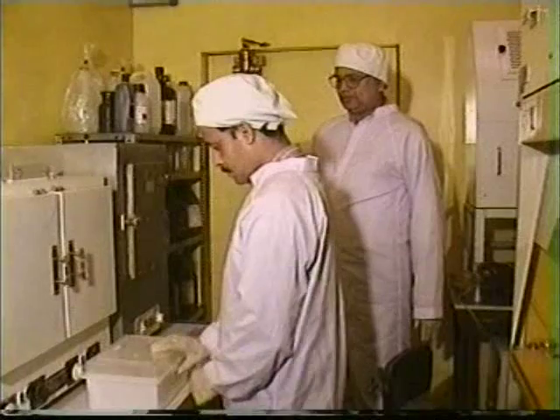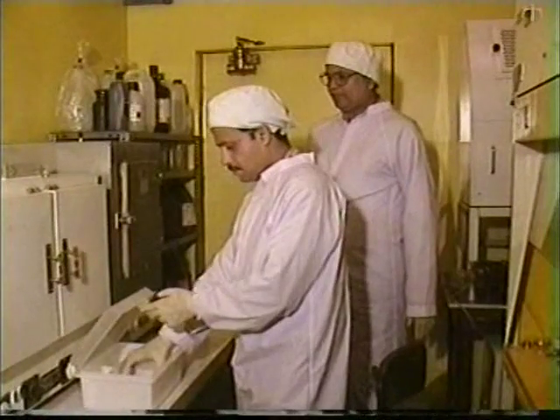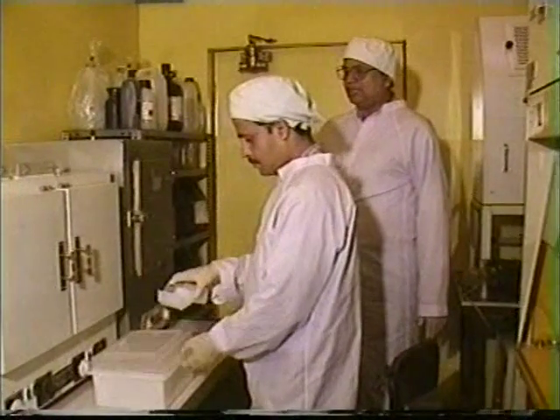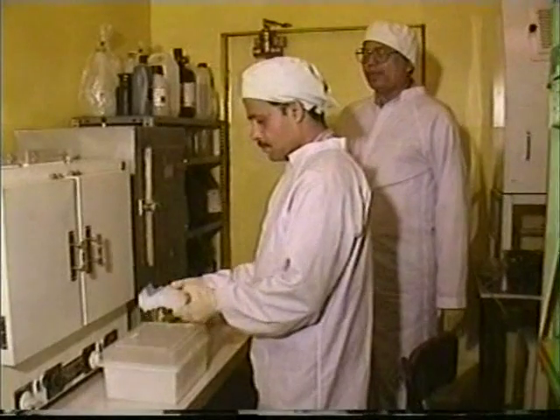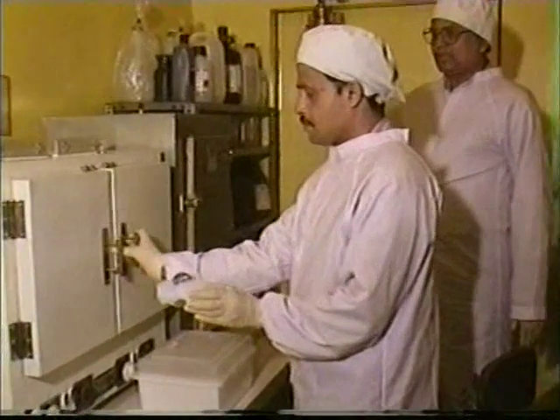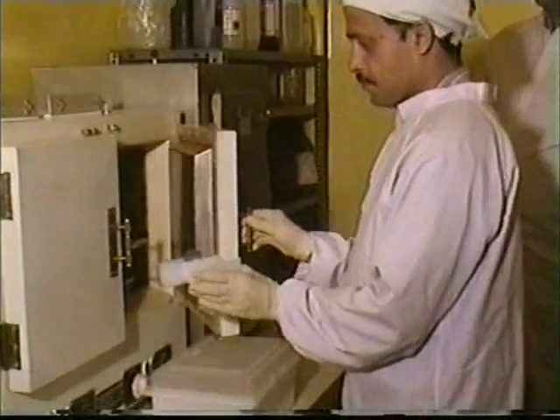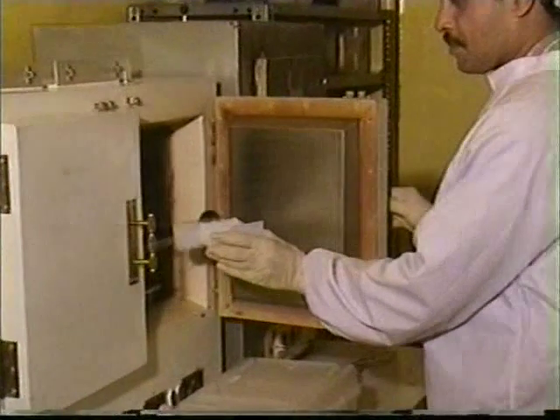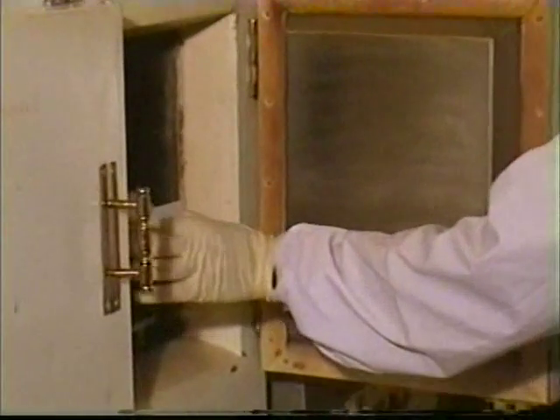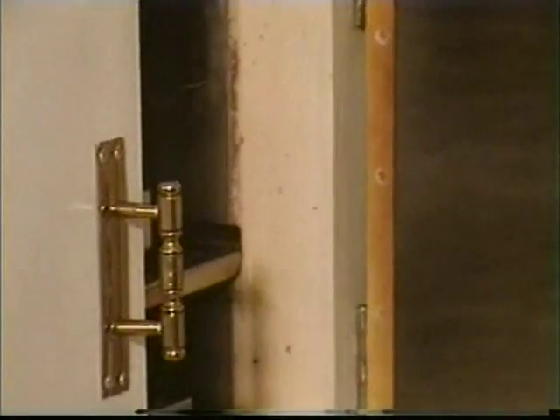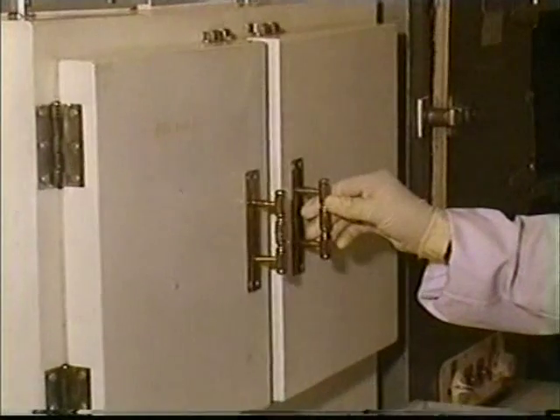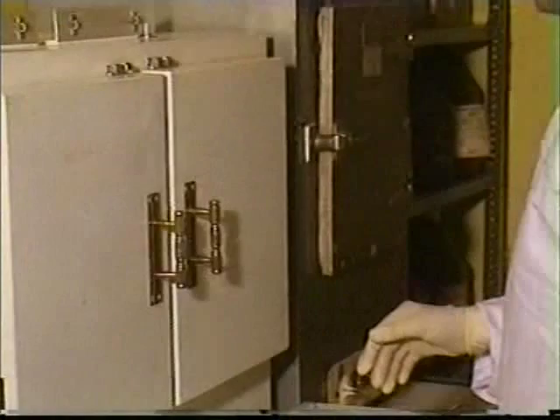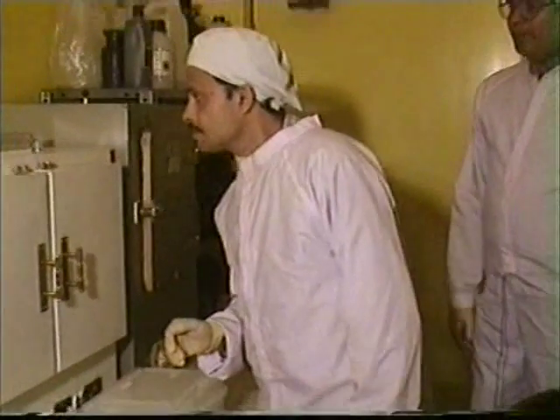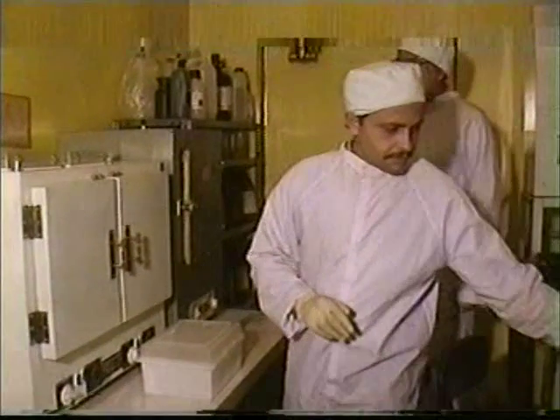Once it is completely dried, the wafer is subjected to post-baking. This stage is essential to harden the photoresist before etching. In this case, we will keep the wafer for 30 minutes inside the oven. Our next step is etching of silicon dioxide using buffered hydrofluoric acid.